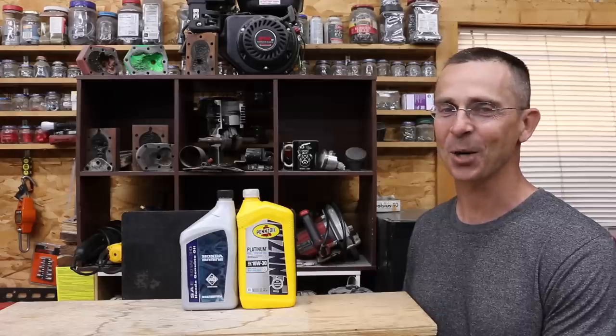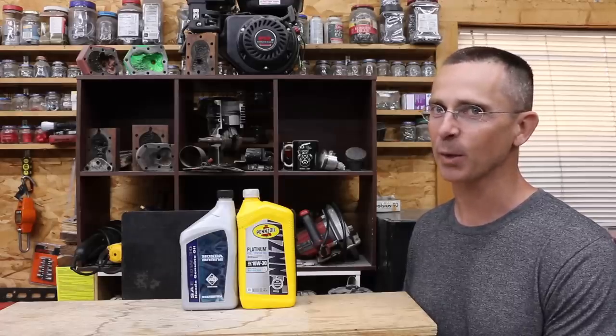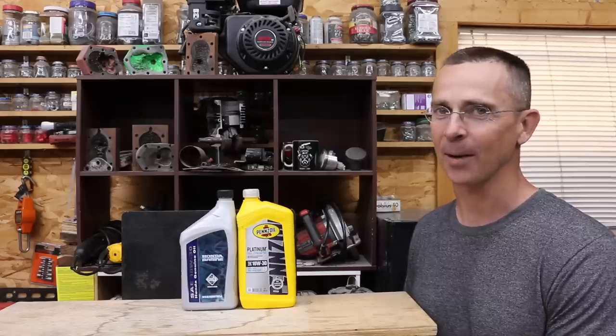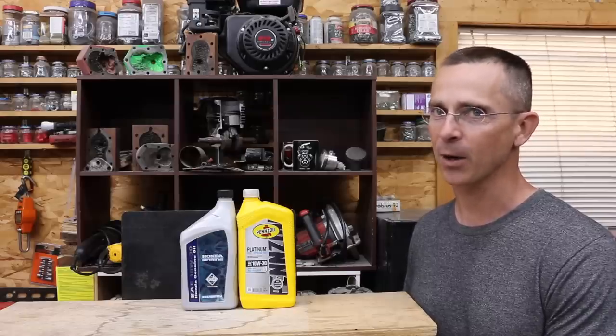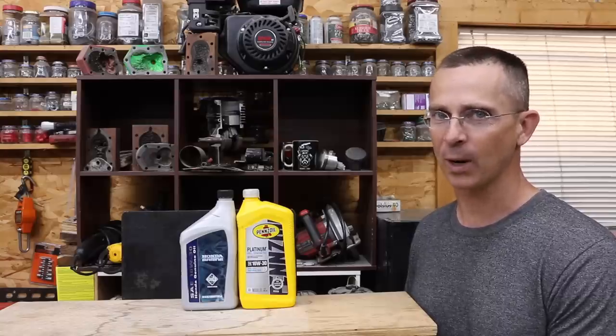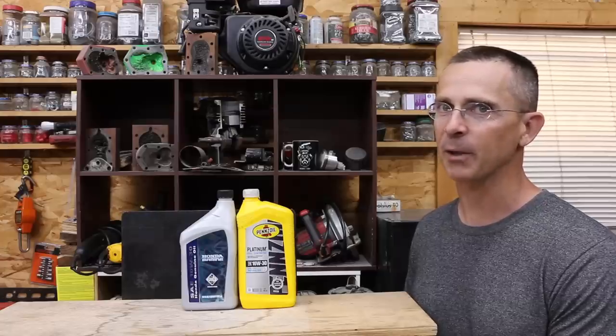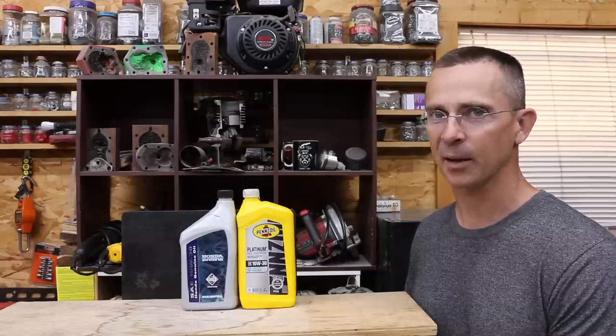So back to the original question, should you stick with oil that's designed for a car or should you switch over to marine oil? In my opinion, stick with the oil that's designed for a car. Unfortunately, the marine oil just did not perform very well compared to the oil that's designed for a car. However, the biggest advantage for the marine oil is the additive package for anti-wear. It does have a lot of zinc and phosphorus. However, in a modern car, you definitely don't want to have too much phosphorus and zinc because that'll cause a problem with the catalytic converter.